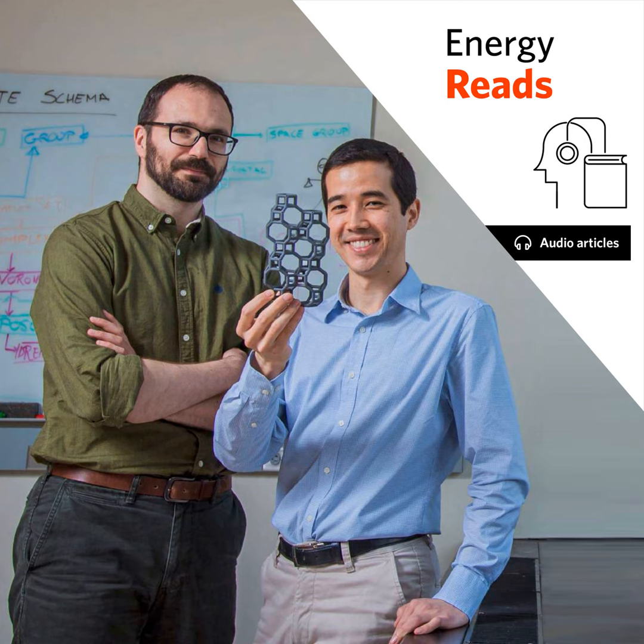While recognizing the value of that metric, the MIT-led team wanted to take more parameters into account. Their new evaluating metric therefore includes not only binding energy, but also the size, shape, and volume of the molecule and the opening in the zeolite framework. And their approach calls for tuning the molecule to different orientations to find the best possible fit.